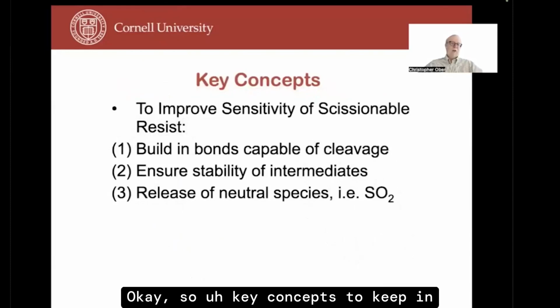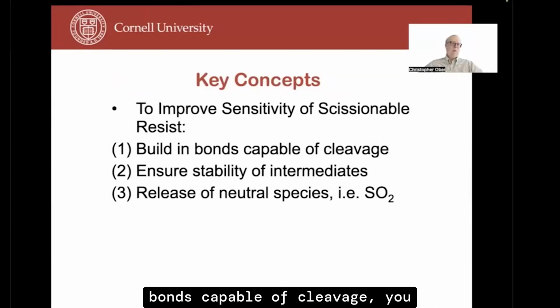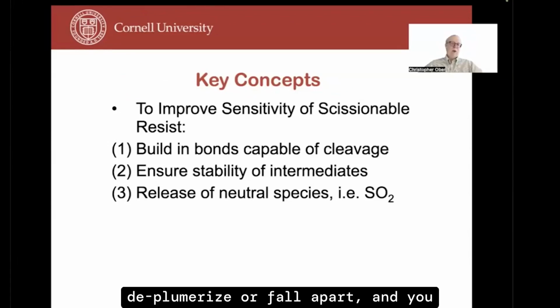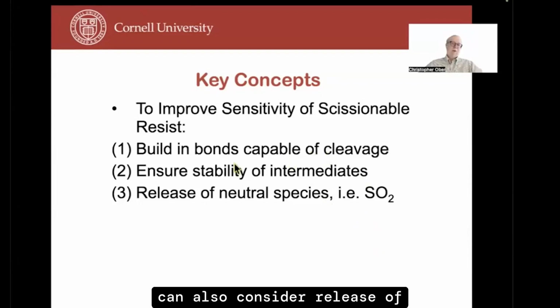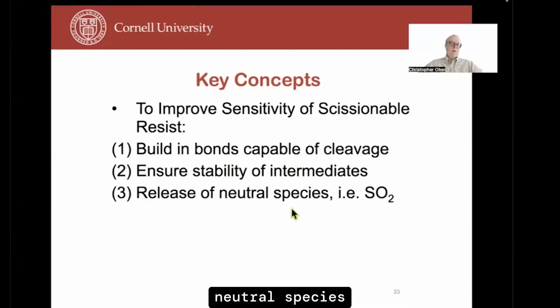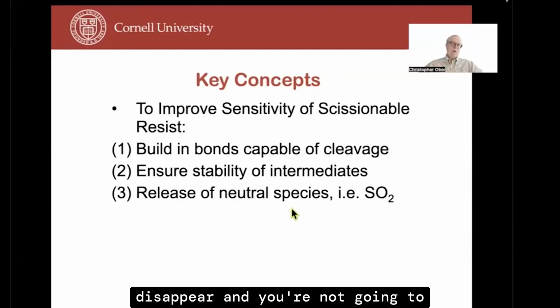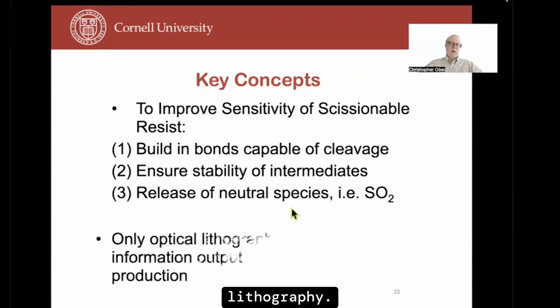Okay, so key concepts to keep in mind for these types of materials are to improve sensitivity of a scissionable resist. You build in bonds capable of cleavage. You ensure stability of the intermediate so it has time to depolymerize or fall apart. And you can also consider release of neutral species. So once it's loose, it's going to disappear, and you're not going to reform a polymer or lead to additional cross-linking. So scissionable systems are all positive tone, and they're seeing a resurgence thanks to the studies in extreme ultraviolet lithography.